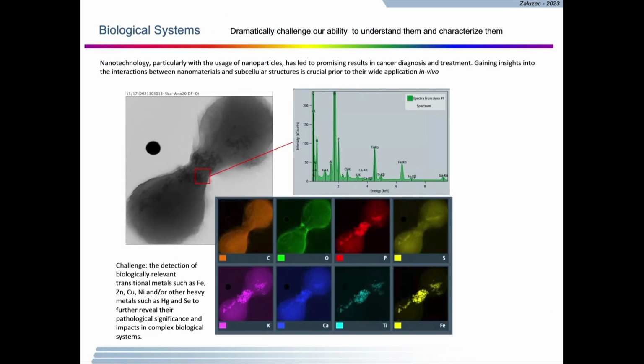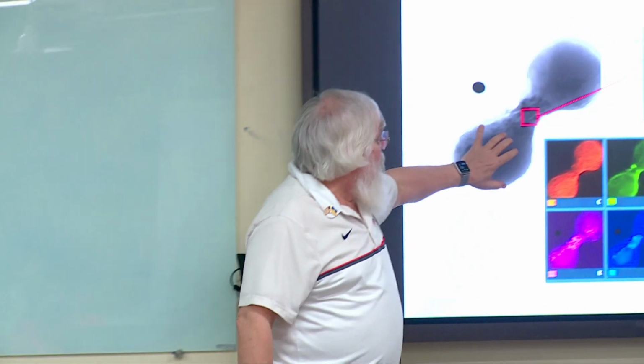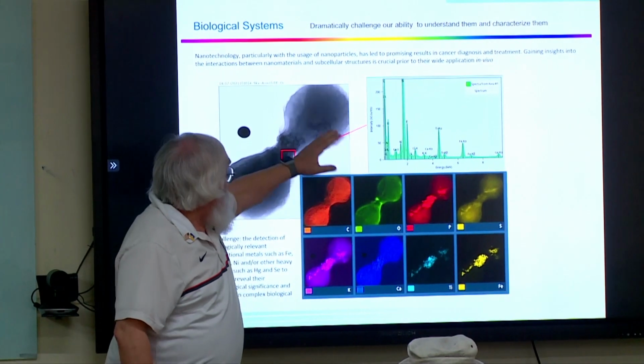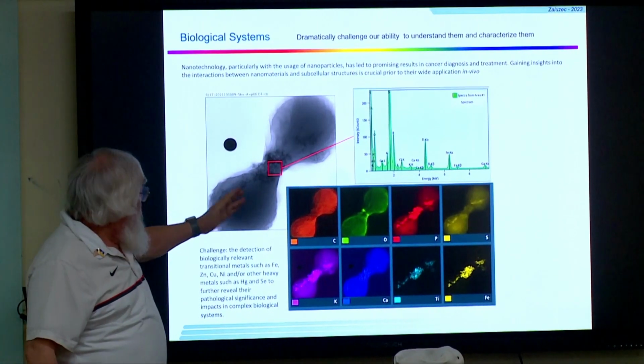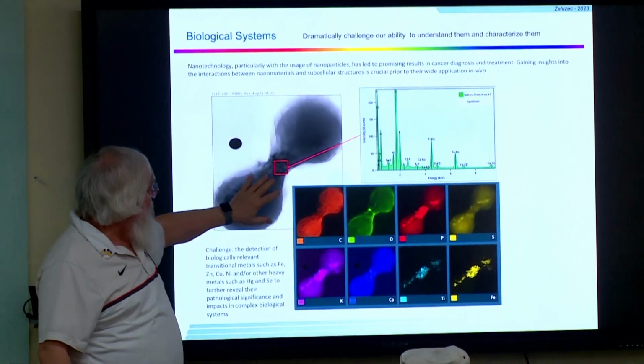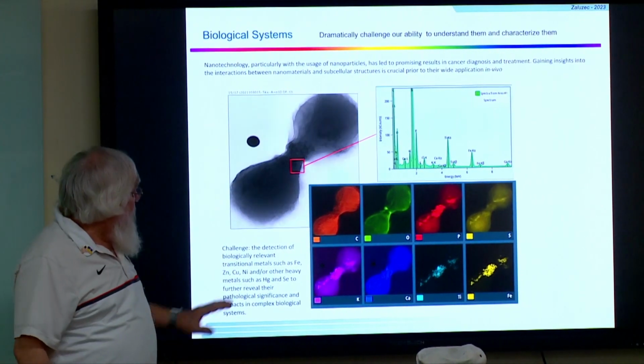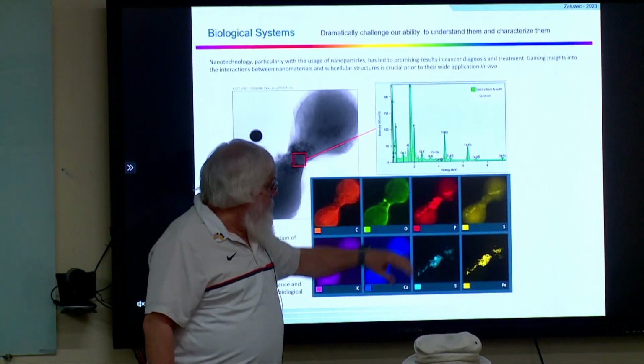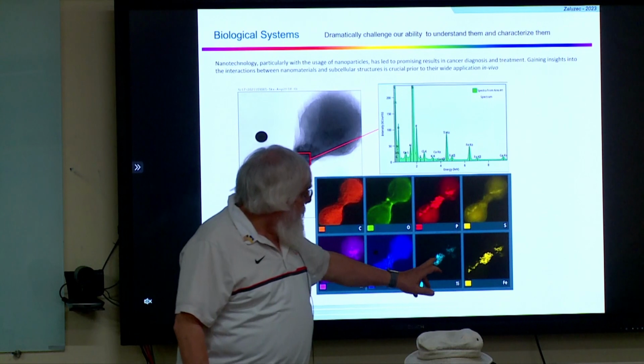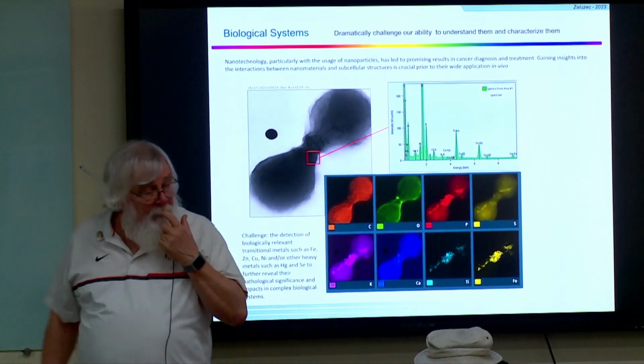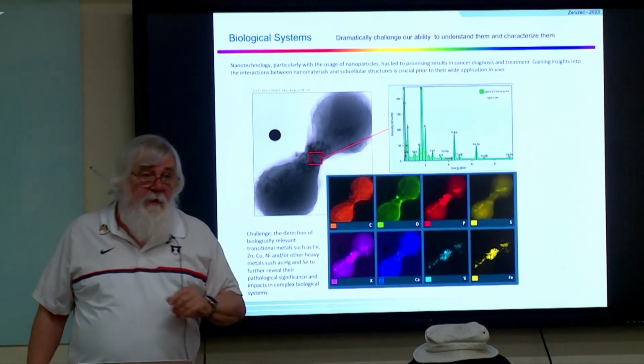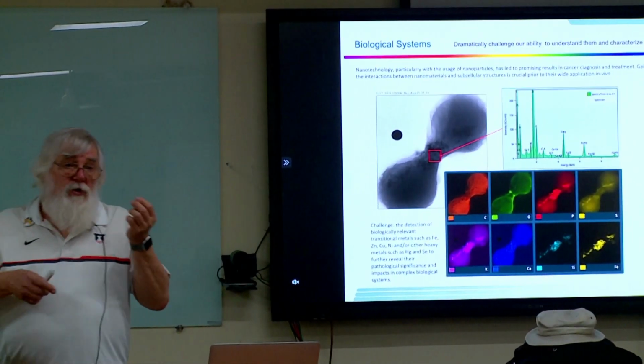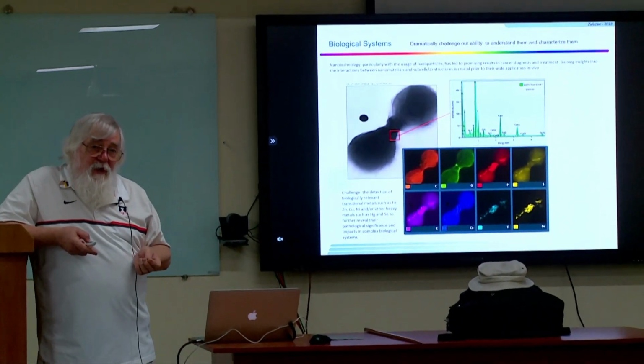And for those of you from the biotechnology audience, if there are a few of you out there, studying cancer, nanotechnology has been used quite a bit nowadays in cancer. These are two full-blown cancer cells. They've grown together, and we see structures inside that. This is a pseudo-tomogram. We're tilting the sample back and forth, and we can see the structures. With modern analytical techniques, I can tell you that, yes, there's my carbon, oxygen, phosphorus, and the like, but importantly, we see the transition metal components in there, mainly the titanium and the iron and a little bit of the phosphorus. So there's a reaction going on in there. Those transition metals in biological systems are extremely important.